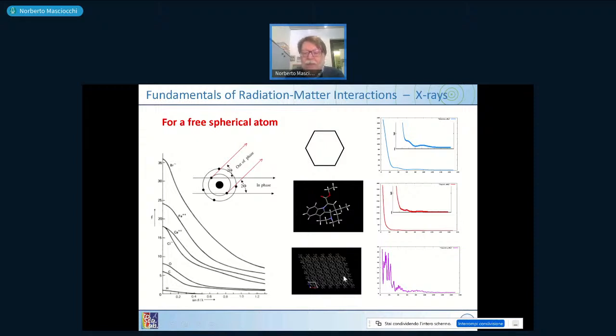We'll come back later to this, but if you take now a larger crystal, not a nanocrystal, a larger crystal, then you can see, and I go back and forth here, that these peaks become sharper, they are more or less located in the same position, and they emerge very clearly from a background. So the crystal is an amplifier of a signal and gives you specific positions where there are some geometric relation and phase relation between the different waves arising out of it.